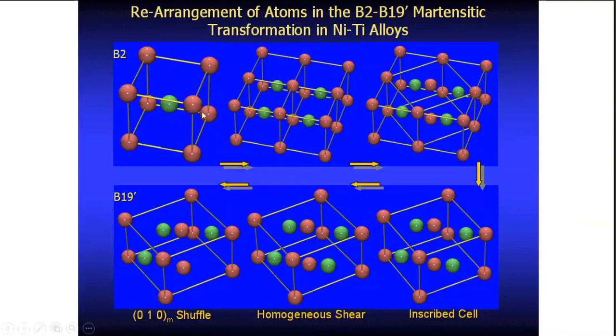So I'll show that in this case in nickel titanium alloys, you start with the B2 structure. And to get to this, again, this is having 2 atoms per unit cell, and this has got 4. So you take 4 such cells and delineate what is a tetragonal cell out of that. And in order to get to this monoclinic, you have to change these 3 axes likewise to the 3 orthorhombic axes. So this is the orthorhombic cell that you get. And then you shear this plane with respect to this, if I call this O1 plane, these 2 planes, we shear with respect to each other. So this angle becomes something like 96.8.